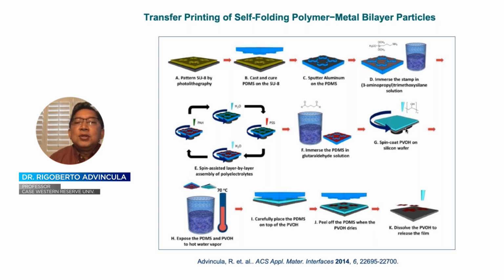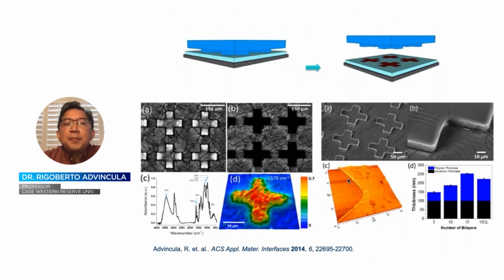So anyway, to continue this illustration, we made these patterns with different patterns using oxygen ion etching to make the template. And then we varied the surface chemistry with polyelectrolytes. And then we stamped these materials on surfaces such that we were able to show what I call the origami effect. So for example, here is the SEM, an optical spectroscopic IR optical imaging, as well as AFM, of those features as shown in this dimension, also about 150 microns.